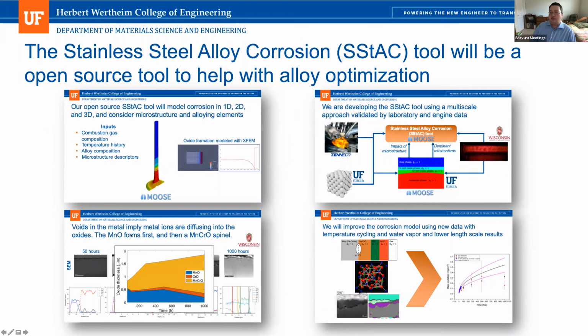And so far, we've been able to show the critical impact of manganese on the corrosion of these valve steels, and how the manganese chrome oxide spinel seems to be the most stable oxide. And we've started out with a preliminary fit for our macroscale corrosion model, but we're now working to improve that fit using additional experiments and also our lower length scale simulation results.